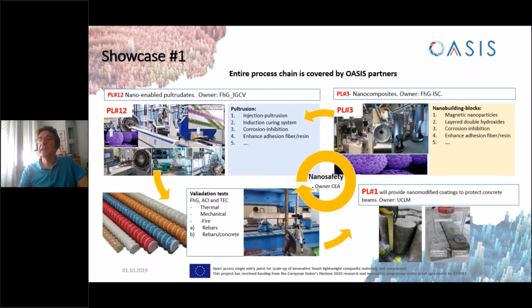Fraunhofer ISC developed several types of nano and microparticles to enhance fire resistance, corrosion resistance, mechanical performance, and curing speed and degree on fiber-reinforced polymer rebars produced by Fraunhofer IGCV. They are focused on processing the rebars by pultrusion using an injection chamber, incorporating the nanoparticles into the resin formulation, and curing the resin using a combined system of infrared radiation and induction, thanks to the use of magnetic nanoparticles.